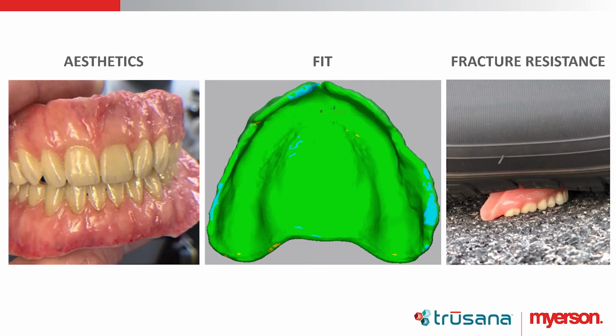A lot of that, I believe, is definitely due to porosity. First generation printed materials were not good at repelling water. They were absorbing water, which made them weak over time and also less stable over time. So we're really looking for materials that allow us to be aesthetic, that fit well, print accurately, and are resistant to fracture. I don't want a patient brushing their denture and have it fall into the sink and shatter. That happened time and time again with the first generation of printed materials.